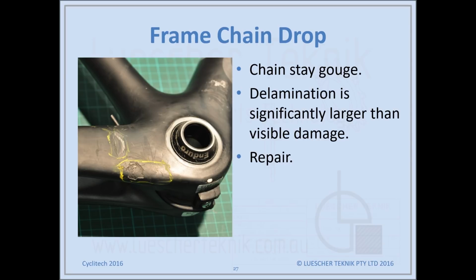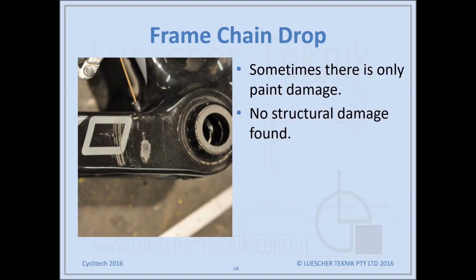In this case, the damage was repairable. In some cases, the delamination can travel all the way through into the bottom bracket bond, which then makes the repair much more difficult, or sometimes not practical.